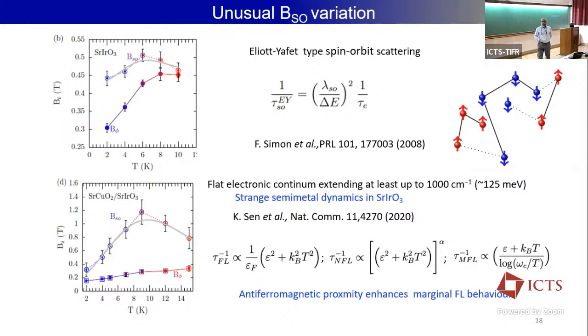Because SrIrO3 does not break the inversion symmetry, we looked into the spin relaxation mechanism. Since it does not break the inversion symmetry, we thought the EY type of spin orbit scattering plays a dominant role here. And for EY type spin orbit scattering, the scattering rate is given by this, where tau is the momentum relaxation time.